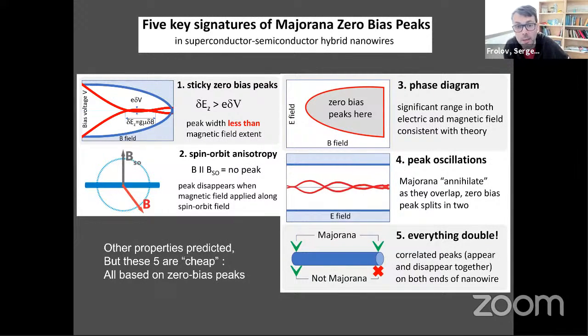And finally, the last one is very important and conceptually simple, but a little bit harder to do in experiment. There should be 2 Majoranas in each wire. So you look on one end, you see a zero bias peak. What happens on the other end? There should be 2 zero bias peaks. They should be correlated. Like if one is there, the other one should be there. If one splits, the other one should split. If one disappears, the other one should disappear. And that is the indication that you have actually created a topological region of this Kitaev P-wave spinless state in the entire wire.